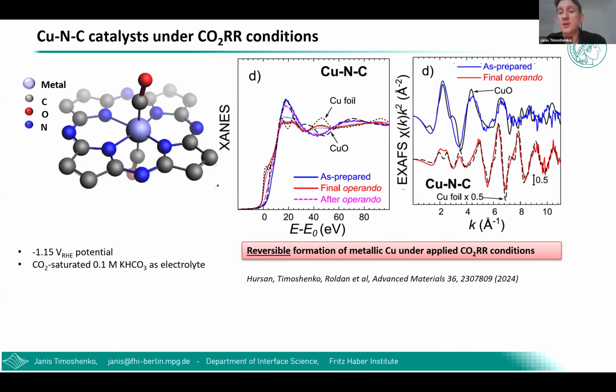But under applied potential, the spectra look completely different and actually match very nicely the spectra for copper foil, but with lower amplitude. So it tells us that under working conditions, under static CO2 electroreduction conditions, these copper single atoms actually don't remain single atoms, but migrate and somehow cluster together, forming copper nanoparticles. So this already is quite interesting, but we also, of course, can now track this transformation in a time-resolved manner.